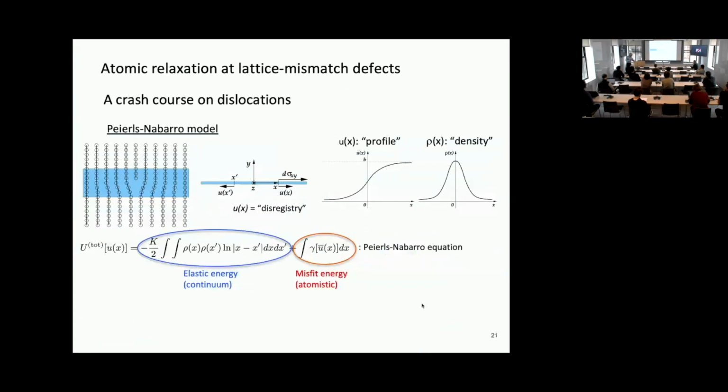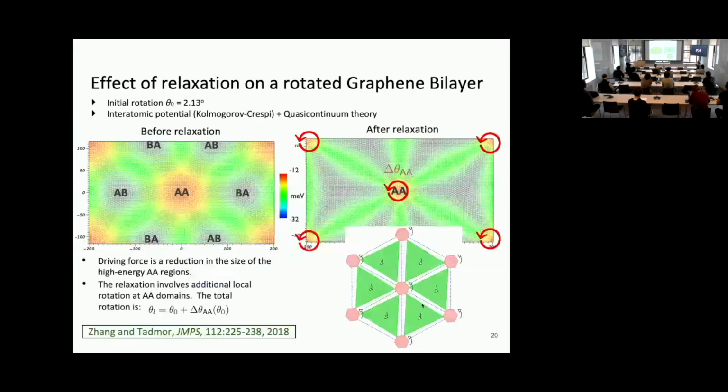And yes, a quick question. Please, yeah, please. Is the lattice mode which produces this localization, is it really essentially entirely a spatial variation of twist, or is there a dilatation in and out also? It's mostly a twist because graphene is very stiff, so there's not much change in bond lengths. And basically, this kind of twist allows the system to take up a lot of the strain that you would have if you simply expanded or contracted these regions.